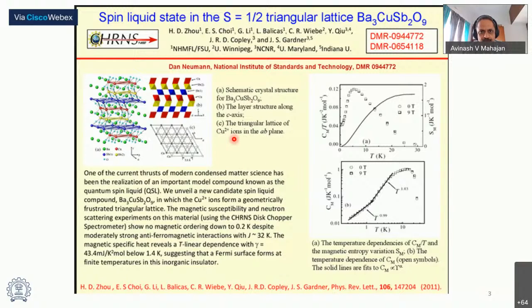So basically you have copper 2+ ions in a triangular plane. And then along the c-axis, they apparently are not well connected. And so that probably promotes this 2D behavior and eventually a quantum spin liquid. There are interesting features in the heat capacity, some linear term and so forth, as you would expect for a fermion case. So these have been dubbed a spinon Fermi surface. These are insulating systems, and so there's interest in such behavior of bulk property.